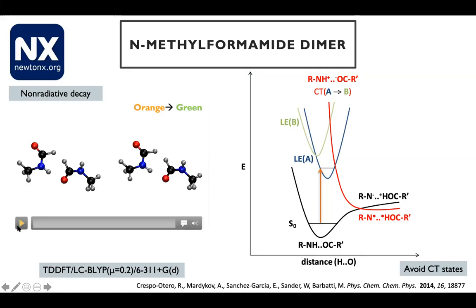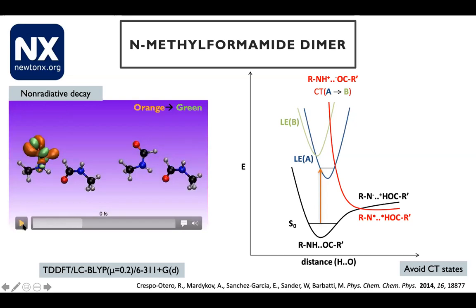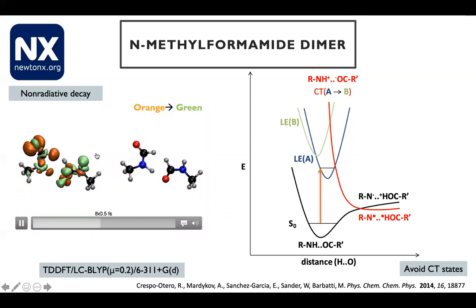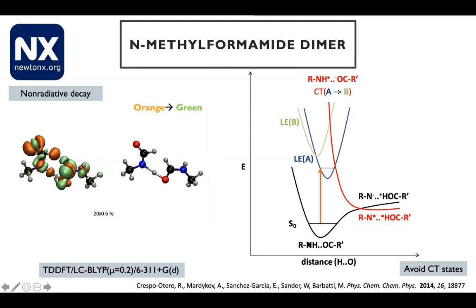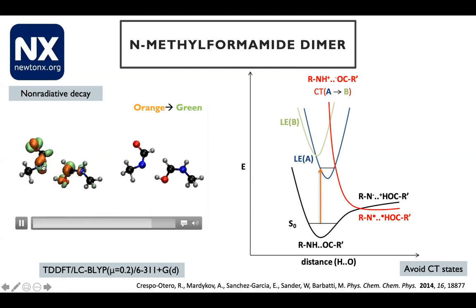This is a simulation that I did quite a long time ago on the dimer of methylformamide. I think it's a good example of what could happen when you go from the molecule to a dimer. Essentially, you excite your system at a local state. You have the electronic density on one of the molecules. This is a local excitation. When the system gets the energy, you have the crossing with the charge transfer state that is coupled with the motion of the proton from one molecule to the other. Because of that, you get to a region of the potential energy surfaces where you have the crossing between the first excited state and the second excited state. This process won't allow the radiative decay, and because of that the system won't show fluorescence or phosphorescence. So this is one of the kinds of processes that could happen.